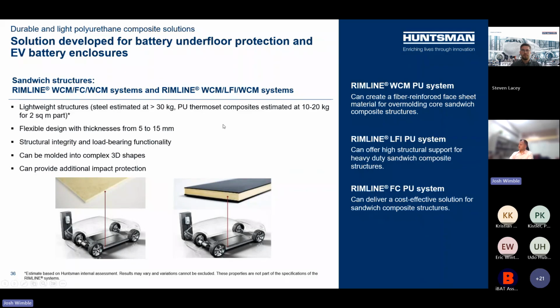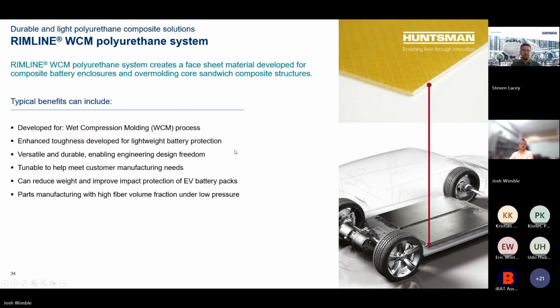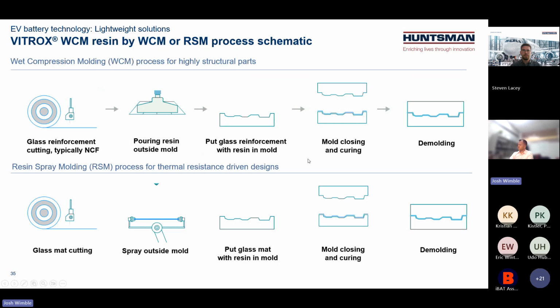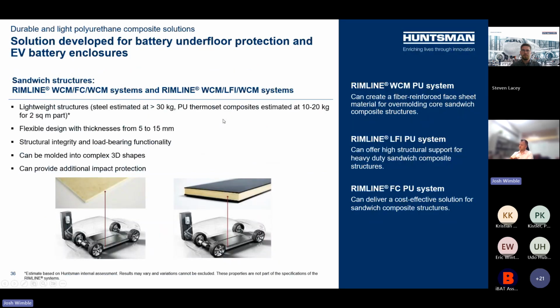So we use that neat skin that I spoke about a minute ago. It's a PU glass fiber or non-crimp fabric outer that bonds to the PU core material, and this neat resin has a fracture toughness of about 580 joules per square meter, which is quite high for thermosets. It's very low brittleness, high ductility and toughness, and so that, with the glass fiber or non-crimp fabric, makes the skin, if you will, of these sandwiches. These sandwich panels will have a foam core or LFI core. They're typically 5 to 15 millimeters thick, and we'll talk briefly about the trade-off in thickness and weight to get the desired impact protection. They can be molded into 3D shapes with some small angles and reasonably deep draws, so ideal for whatever aerodynamic underbody design you have for your battery pack.